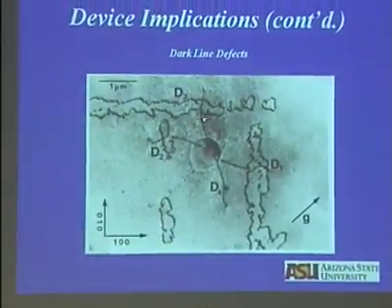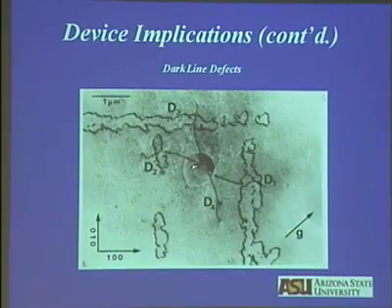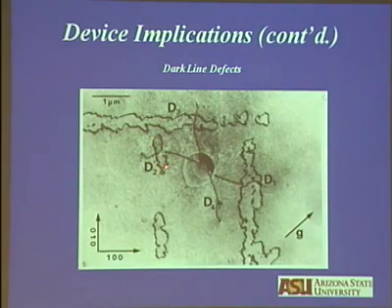Now look at those dark lines, and what you see is something those who do dislocation theory will be enamored with. This is a dislocation in the layer. It multiplies, highly crinkled, showing that climb is occurring in these materials in the development of the dark line defects. And this is another dislocation multiplier. It already tells you that if you want to make reliable lasers, you had better reduce the dislocation density to a minimum in your material. Now the structure, these are the dipole structures.